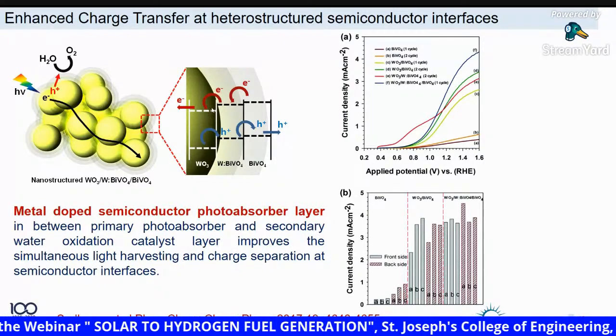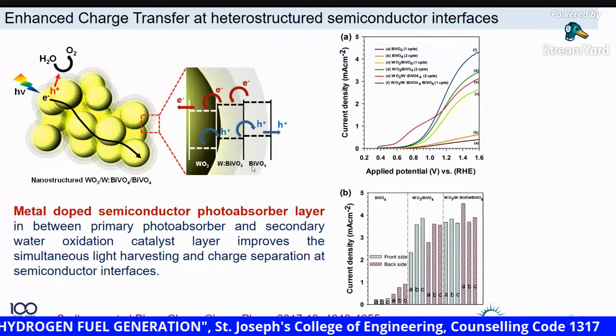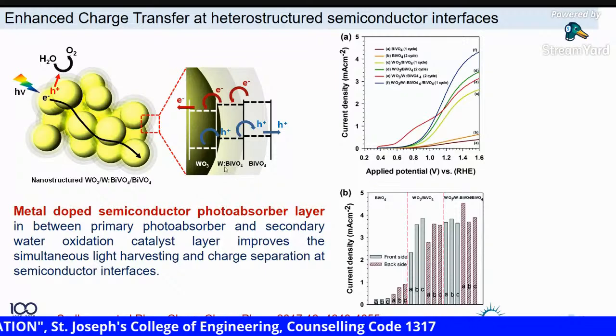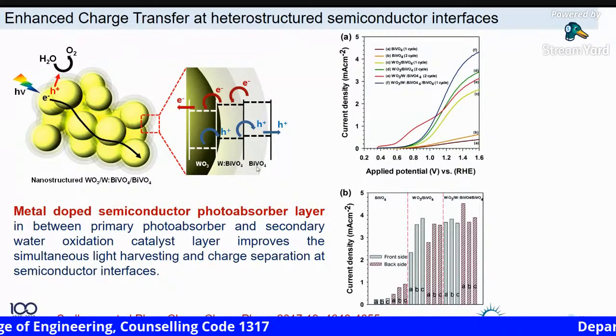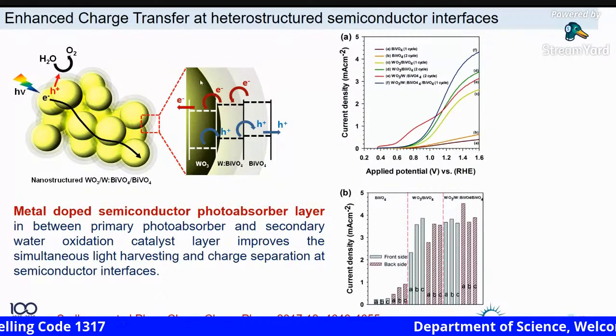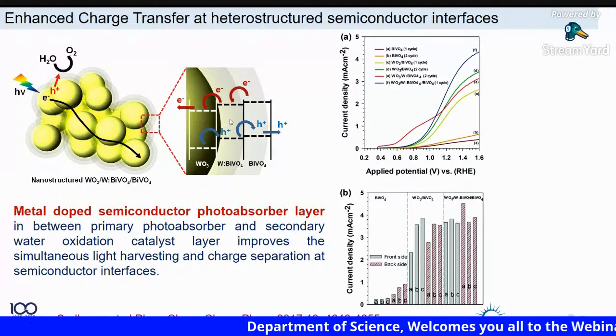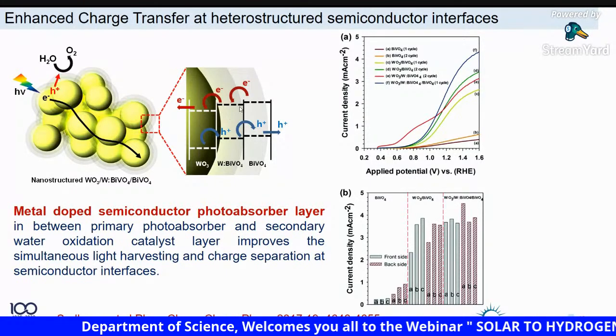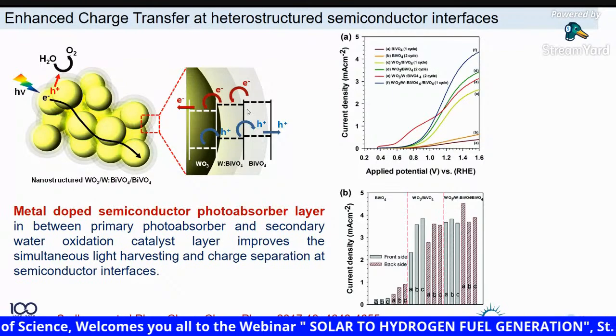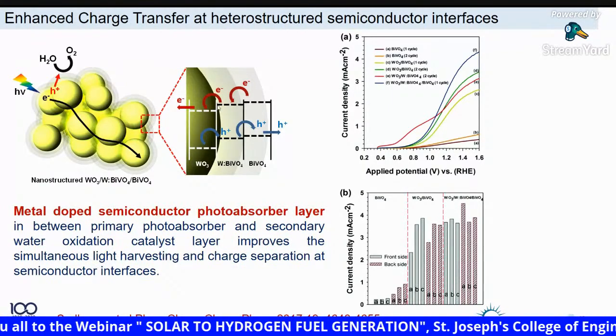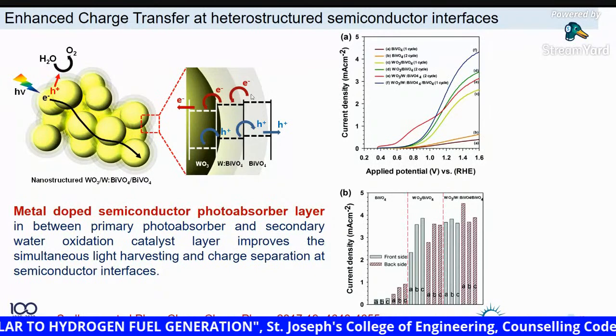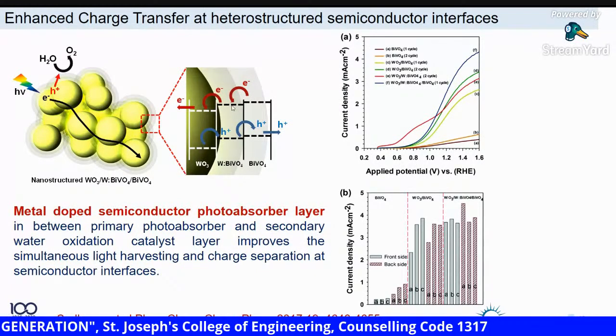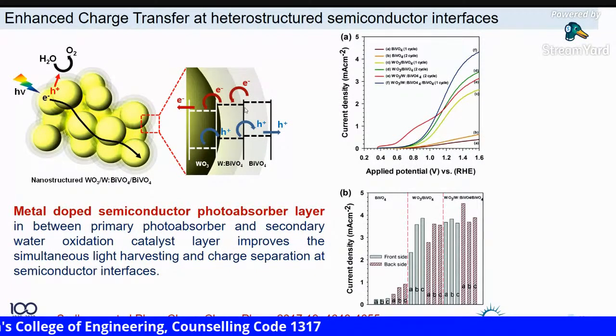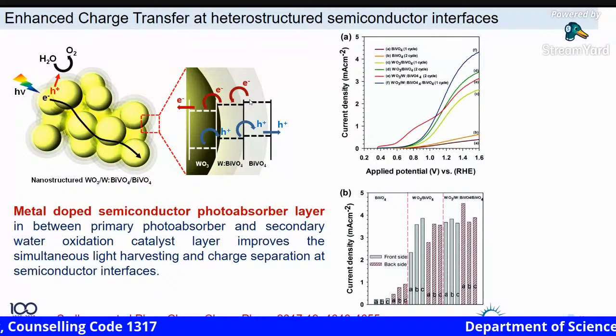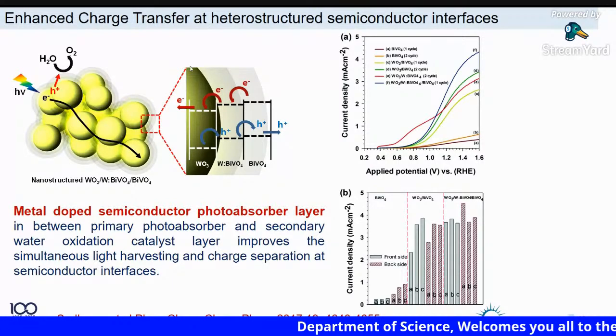So what we did was some metal doping in the secondary layer. That means tungsten-doped bismuth vanadate, for example, and then we inserted it in between the WO3 and bismuth vanadate. So eventually it created a step-type pattern. From a physics point of view, it is a type 2 energetic structure. So instead of the flat energetic structure, these kinds of steps facilitate the photoelectron injection very rapidly from the point of injection to your charge collector area.